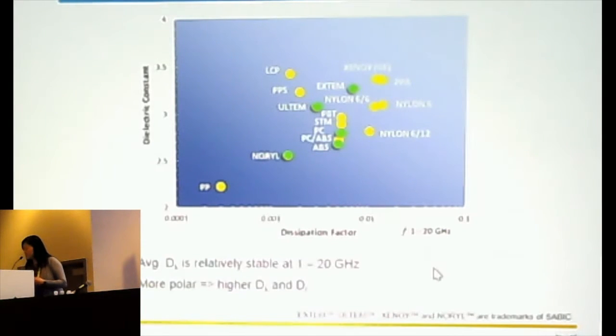And this chart is showing between 1 to 20 gigahertz. In that range, the majority of the thermoplastics are relatively stable, and the permittivity is gradually decreasing when you get to the higher gigahertz range. Among these, we have Noryl, which is high heat PPE, and Ultem, which is a high temperature polyetherimide material. You can see the dissipation factor is below 0.01. If you look at other materials, they either have a higher dissipation factor or a higher dielectric constant. This is basically determined by the molecular structure of the high temperature materials.